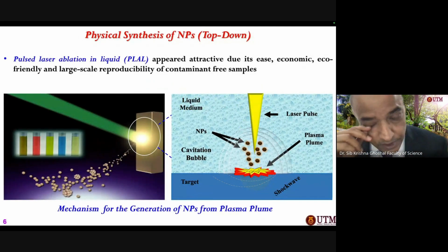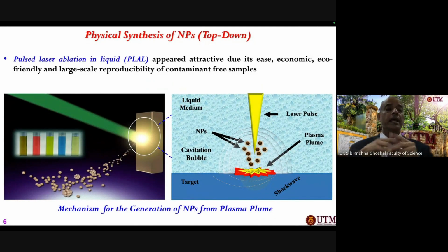So one of the methods people have recently found out is an optical-based technique called pulse laser ablation in liquid. In this kind of technique, we can use a solid pure target of the material, such as silver, gold, copper, whatever nanomaterial we need, even organic material. We directly shine laser pulses on them, fragment the material, and through a mechanism called cavitation bubble and plasma plume generation, these tiny fragments from the target material are dispersed into the liquid.